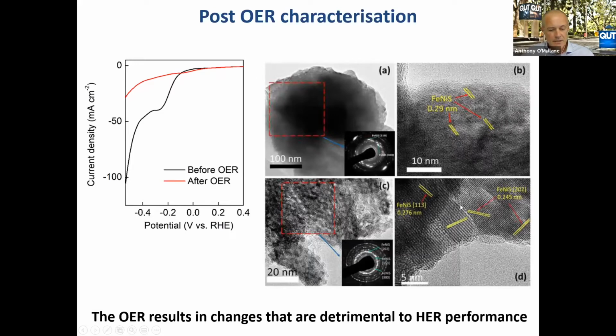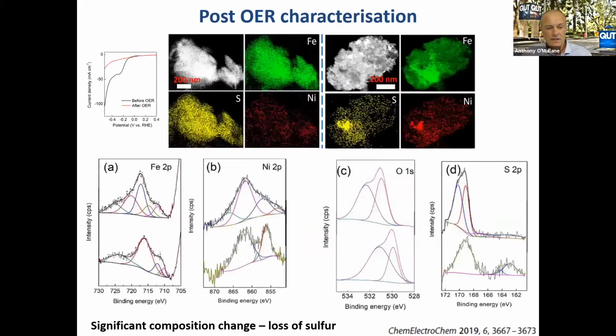So for some reason, that is good for oxygen evolution performance, but not for the hydrogen evolution reaction, and we had to understand why that was the case. What we found was that we're losing a lot of sulfur from our material. During the oxygen evolution reaction, the sulfur was being oxidized into sulfate, basically being lost from solution. So this nice metal sulfide material was no longer available at the surface to perform the hydrogen evolution reaction. That leaching of the sulfur really impacted our hydrogen evolution reaction performance.